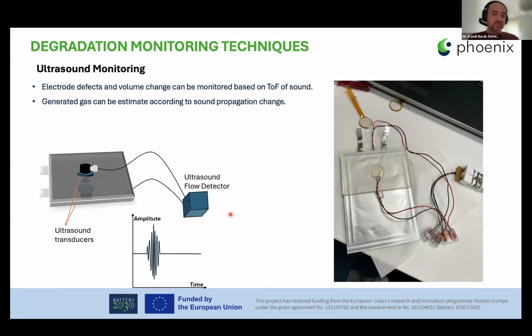Another example of degradation monitoring techniques is ultrasound monitoring. Electrode defects and volume changes can be monitored based on the time of flight of the sound. We simply have two ultrasound transducers, one on top and one below. If we are able to align them appropriately, we simply measure the time of flight of the ultrasound. This will give quite a lot of information about the electrode defects happening inside the cell and the volume changes.